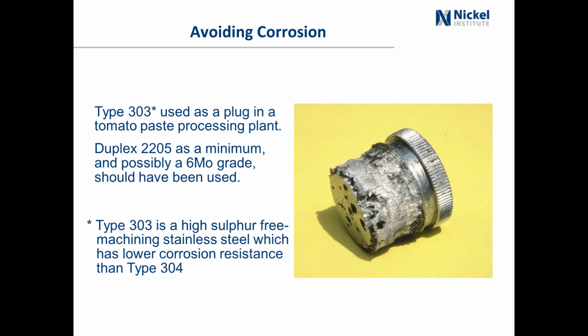The sulfur creates a lot of sulfide inclusions in the material, which are sites for pitting corrosion. So if you've got any chloride present, the chloride is going to attack where the sulfide inclusions are. So 303, even though it has the same chrome and nickel content as 304, it's just not as good because of all the sulfur in it.